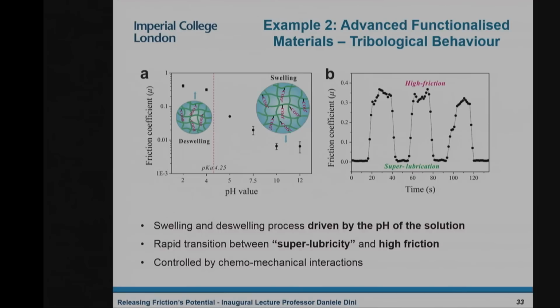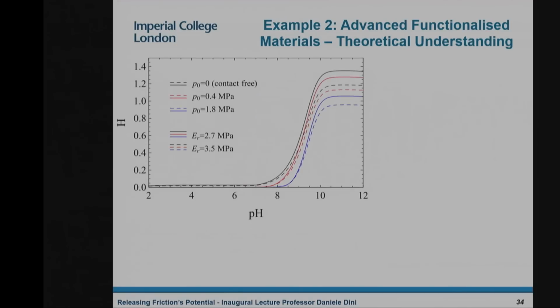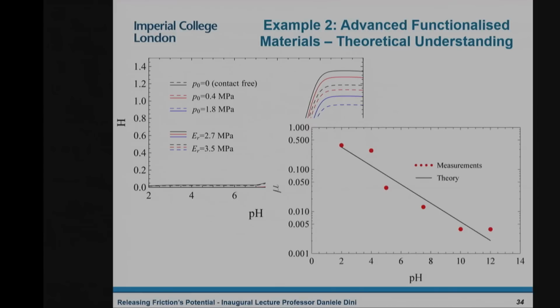And then our theory showed that this is due to the fact that for different pH, and I'm not going to say what this hydration is, basically, the principle is very simple. If you go very high in pH, you start swelling your hydrogel. Swelling hydrogel means you've got more lubricant available to replenish the surfaces. Friction goes down. And in fact, it can go down dramatically. You can talk about friction changes of 2 orders of magnitude just by changing the pH of your solution for these systems.